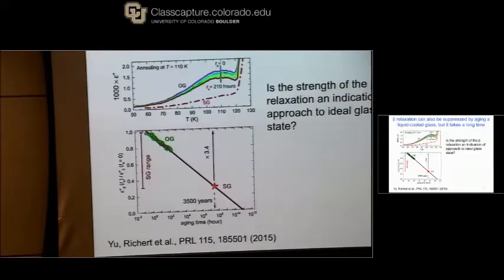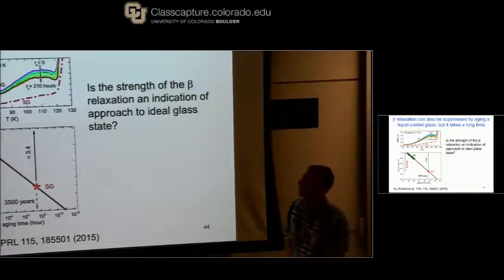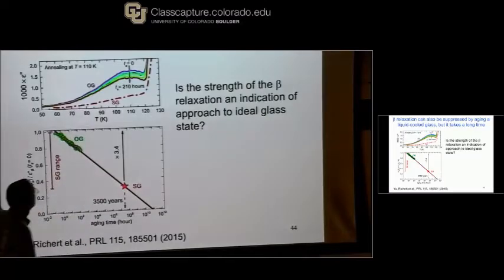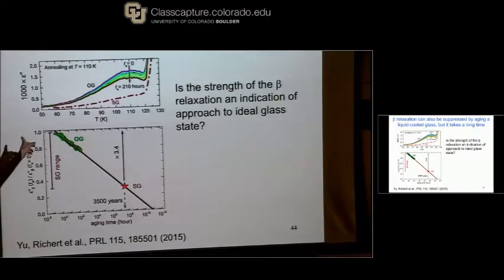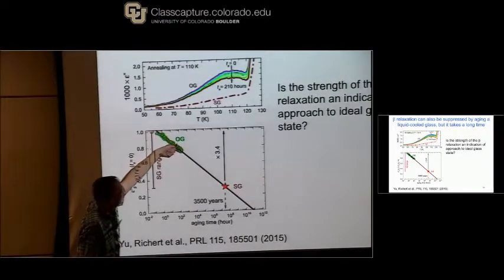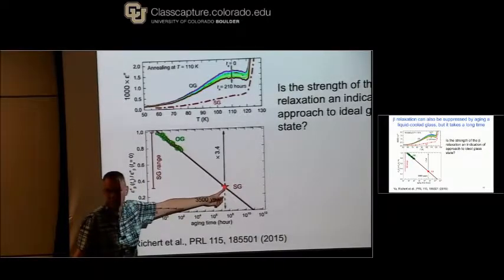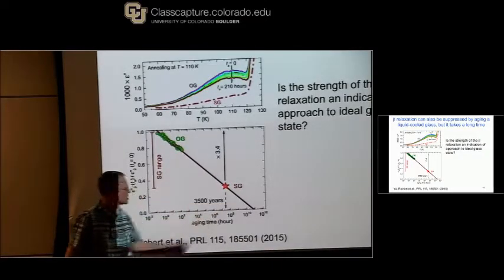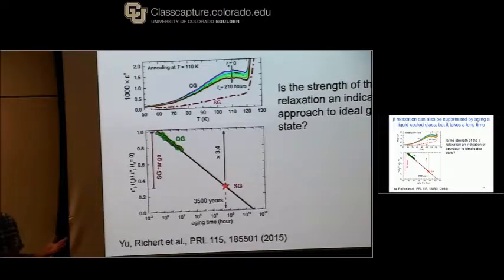Okay, so to put this in context, we said, well, let's try to age a liquid-cooled glass. So we made a liquid-cooled glass. We went a few degrees below Tg to 110 Kelvin, and we repeated this dielectric experiment over and over again. We waited up to 200 hours, a little more than a week. We did see that we started to suppress the beta process as we moved down the landscape. And then, this is what we measured as we aged the ordinary glass. This is what we measured in the vapor deposited glass. And so this estimate would say you'd have to age for about 3,000 years in order to achieve that same stability.